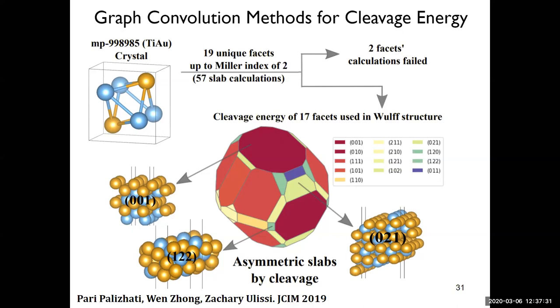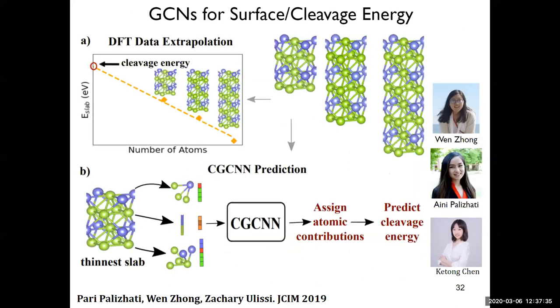Anyways, we can do calculations. We can collect these cleavage energies. There's a standard procedure: you do three different thicknesses, you extrapolate back to zero thickness, and you get this cleavage energy. Basically, the same CGCNN model that worked for bulk inorganic materials also seems to work for surfaces, with just a little bit of tweaking. That was very interesting.